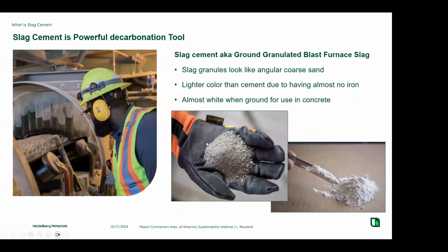And when you do that, you produce these and you put them in what we call a granulator. That equipment, that quenching process, ensures that you come up with this material. This is granulated blast furnace slag. We take that blast furnace slag and we grind it very fine and it becomes a cementitious material.